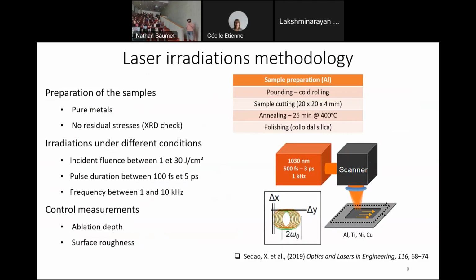And then we irradiate those samples with very different fluence, so these are the incident fluence, between 1 and 30 joule per centimeter square, and with various pulse durations, also between hundreds of femtoseconds and 5 picoseconds, in order to have a large range. So we are scanning the surface of the samples with such a procedure with the scanner, and then we are